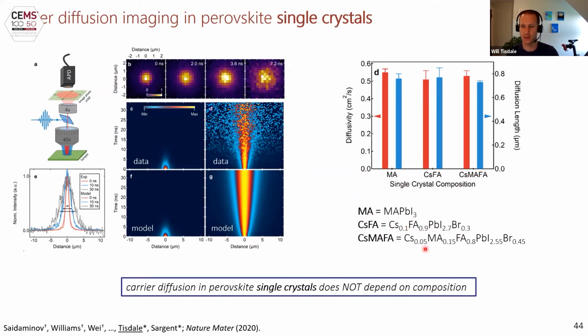And then we have a 3-component cation that's an iodide bromide mixture as well. And the diffusivity in all cases is about 0.5 centimeters squared per second. That's very close to what we were expecting based on others' reports, but there was no dependence on composition. We were surprised because these materials make very different efficiency solar cells. Why did we not see a difference in the charge carrier transport behavior?